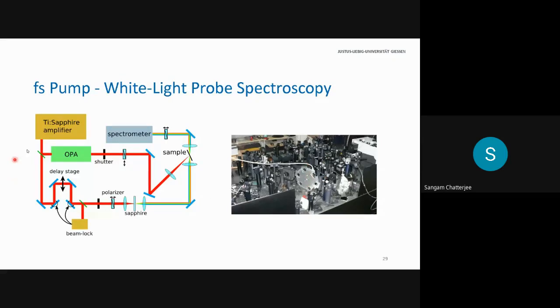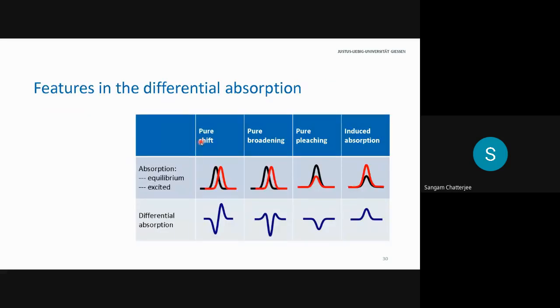On the right-hand side, we have an amplified optical system. We can generate pulses of virtually every color. We generate a white light continuum, which is a delayed white light with sub-100 femtosecond time resolution. We can measure the transmission through a sample, and then we apply Beer's law and study the changes. And there are certain changes that you can have here. I always like to call this slide pump and probe 101. If you think of a resonance, the resonance can do certain things.